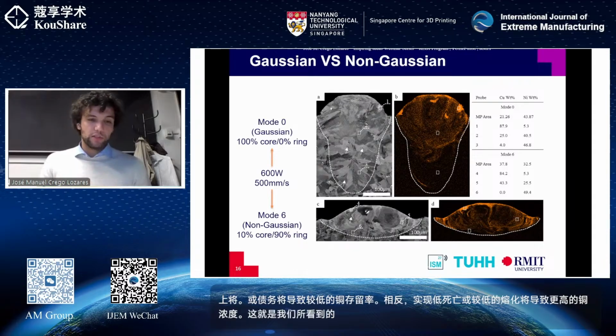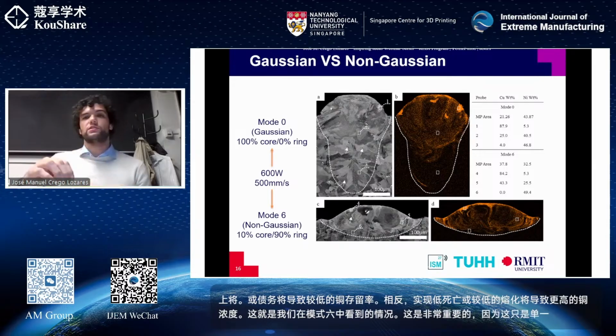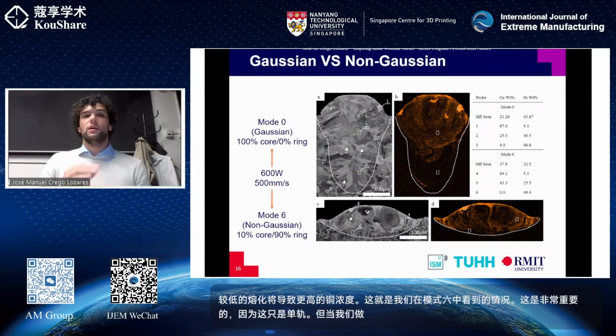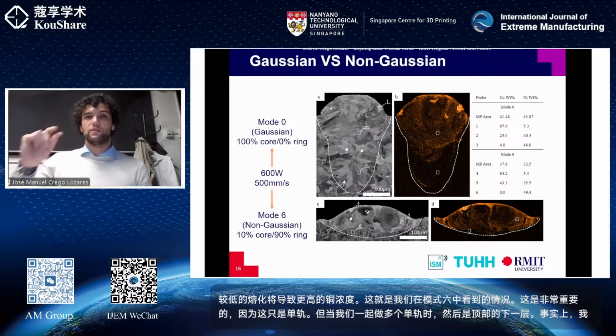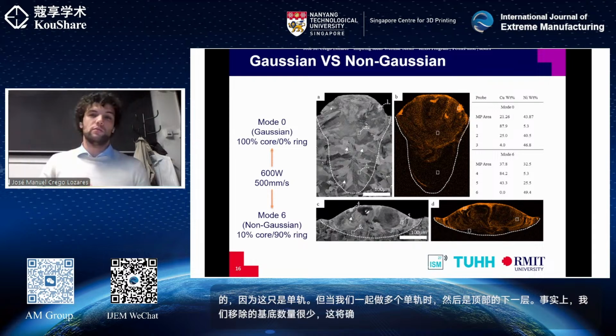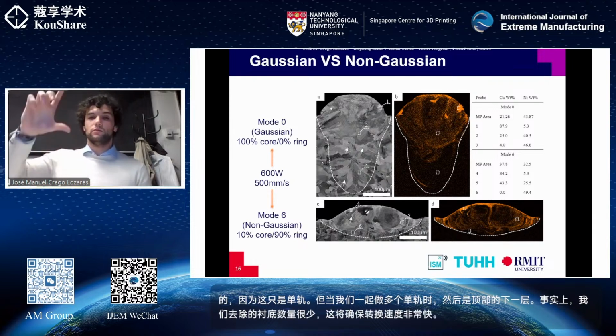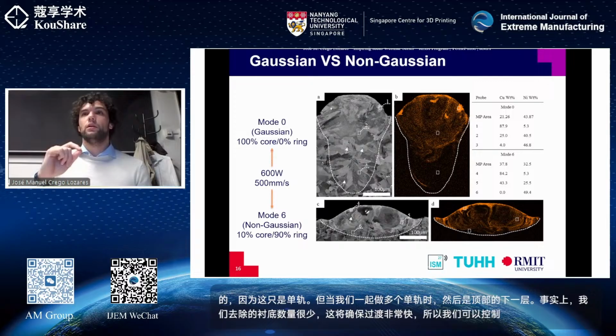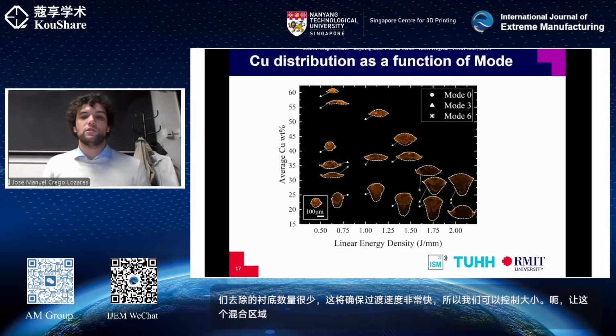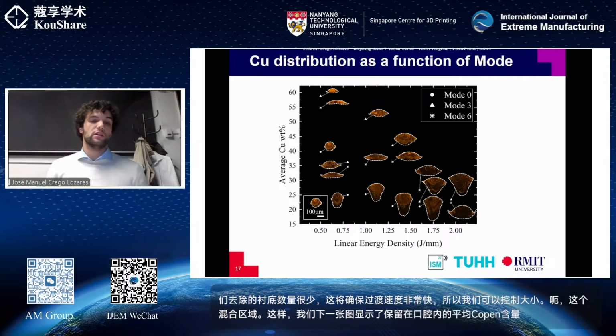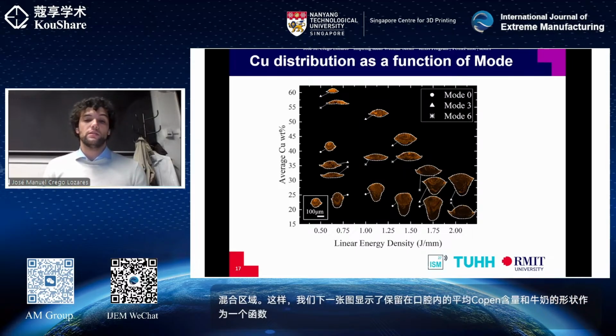This is key important because this is just single tracks, but when we do multiple single tracks together and then the next layer on top, the fact that we are remelting very little of the substrate will secure that the transition is actually very fast. So we can take control of how big or small we can make this intermixing region. In this vein, the next graph shows us the average copper content retained inside the melt pool and the shape of the melt pool as a function of the energy provided with the laser source.